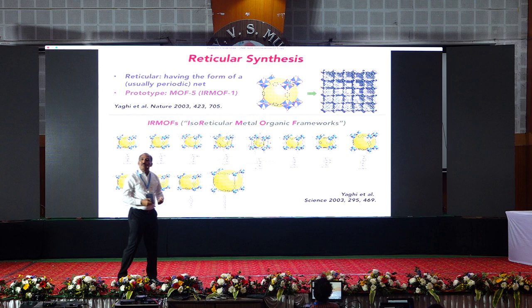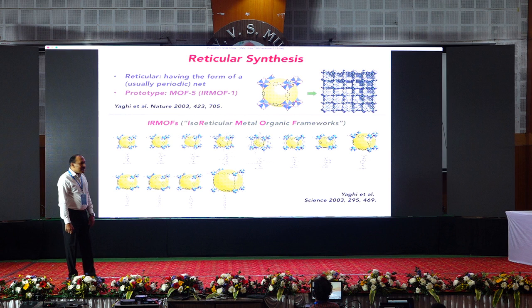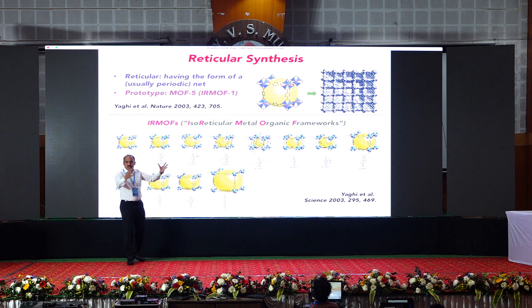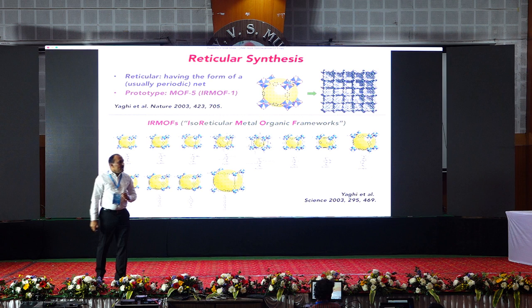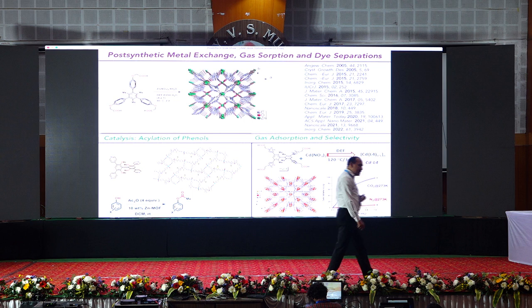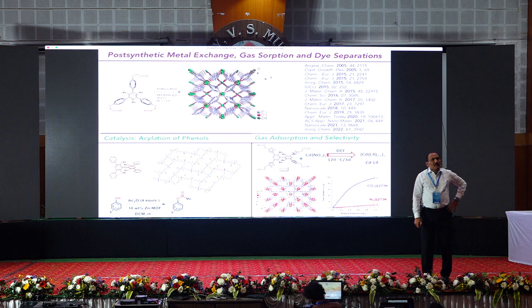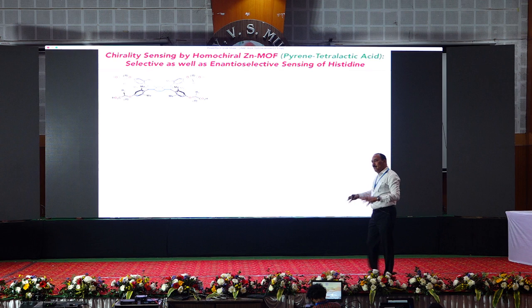This work was pioneered by Yaghi, who showed that by dealing with different organic spacers and using metal ions, you can construct porous materials at your will, and they have come to be popularly called metal organic framework structures. And we have been working on this for quite some time. In fact, ours is the first group to have gotten into these materials, starting with the first paper in Angewandte Chemie in 2005. So there's a lot of work, but I'll try to show you one example of how to build porous materials, starting from molecules, right?